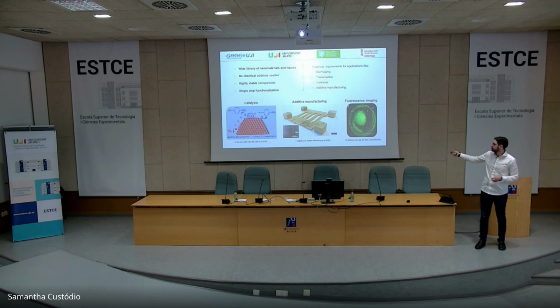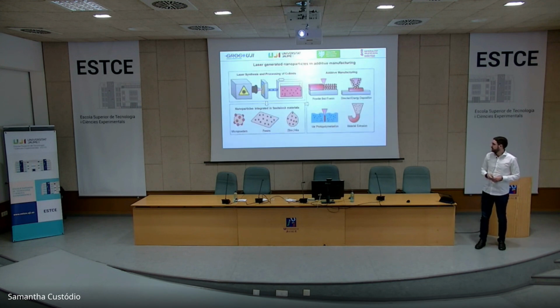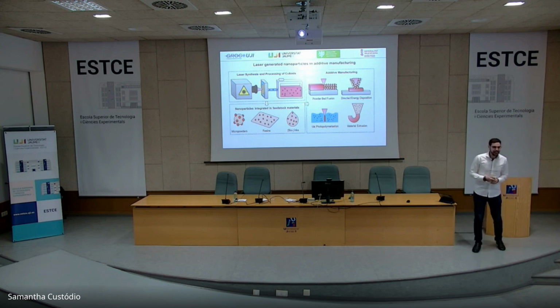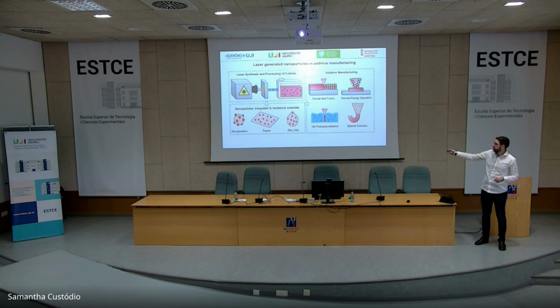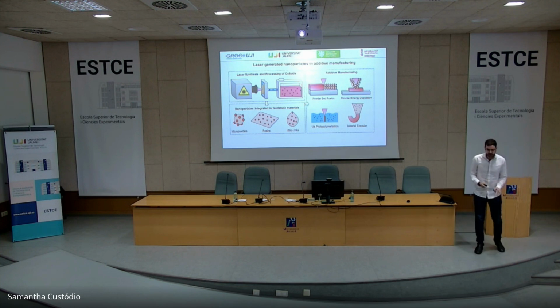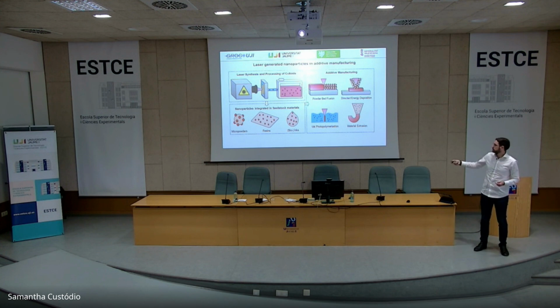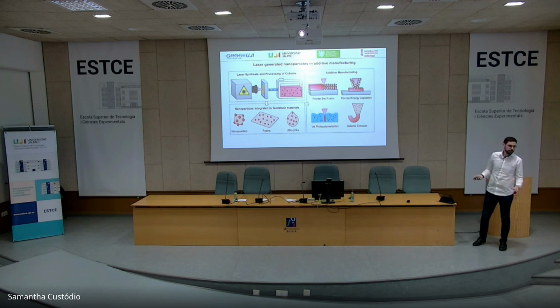Today I will focus mostly on the additive manufacturing part. So here I return to my previous slide. I have shown you a bit of the advantages of this laser nanoparticle generation. And now what I want to show you is the main process of how we take them and put them in one material, in this case, microparticles, and then we do some printing with, for example, powder bed fusion. I will do it first taking silver, putting it in microparticles, and using powder bed fusion to generate bactericidal parts, bactericidal materials. And in the second case, I will show a photopolymerization example where we add some nanoparticles to the resin, and then we print some magnetic actuators.